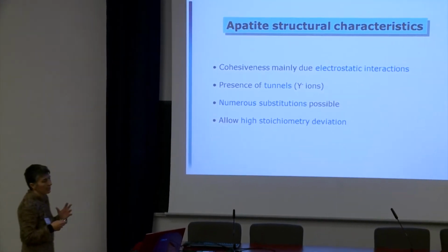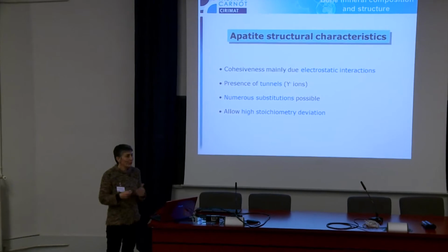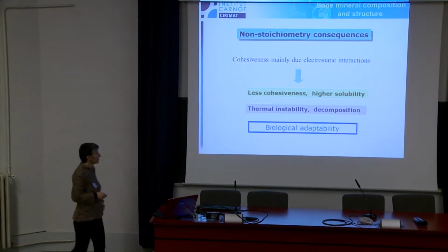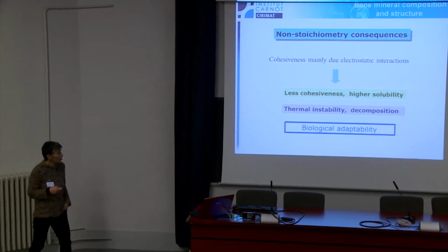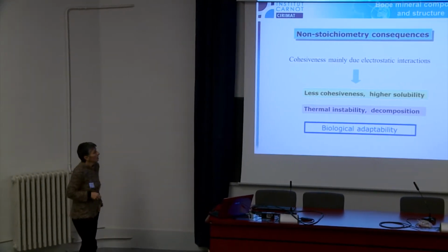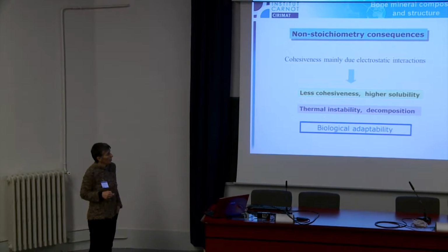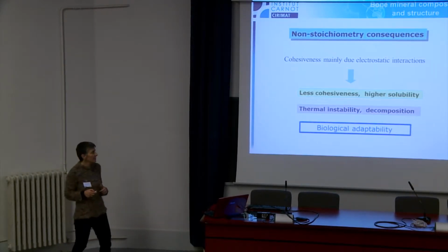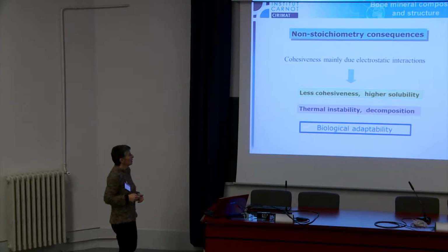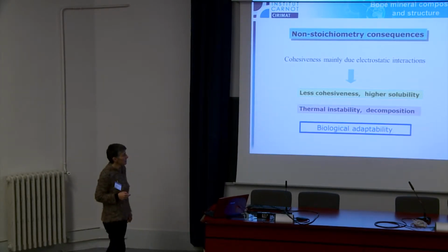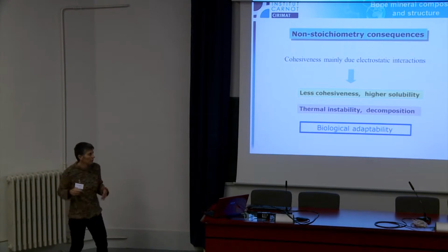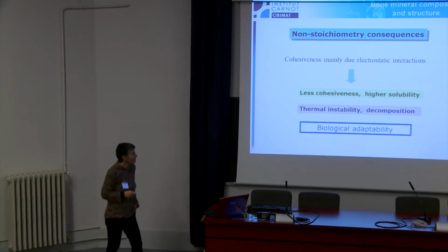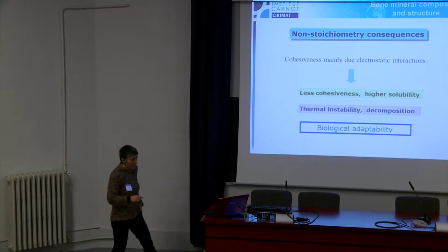All these characteristics are responsible for the possibility to adapt the structure. The consequences of non-stoichiometry are less cohesiveness of the crystal, so higher solubility, more reactivity, and thermal instability, but in the body the thermal variation is not important, and so there is biological adaptability.